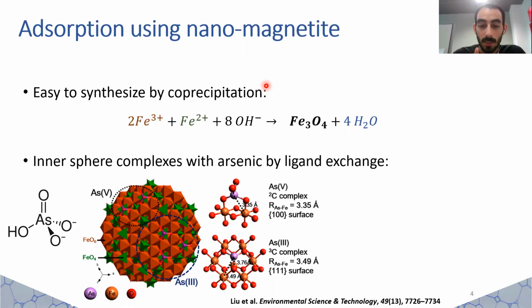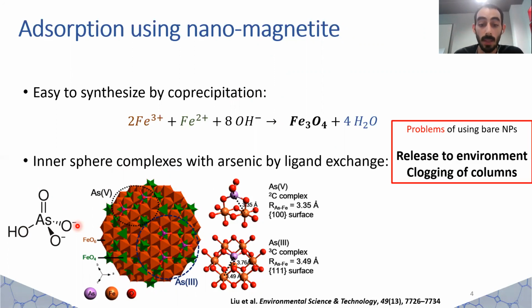Nanometric magnetite is easy to synthesize by coprecipitation of ferric and ferrous salts in basic media, and adsorption on its surface occurs mainly by ligand exchange, in which arsenate species form inner sphere complexes with the crystal structure. A slightly acidic media favors this reaction. The main problem of using nanoadsorbents is their potential release to the environment and the clogging of filtration columns as a result of particle agglomeration.